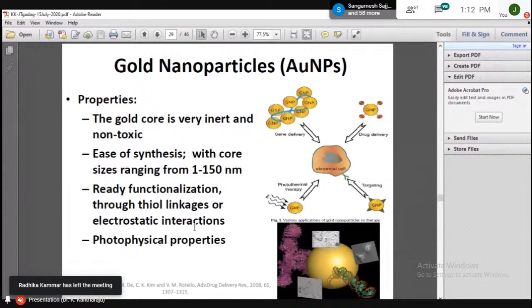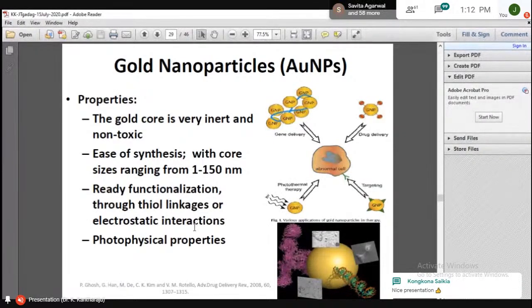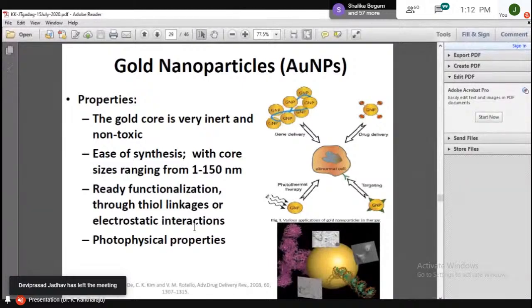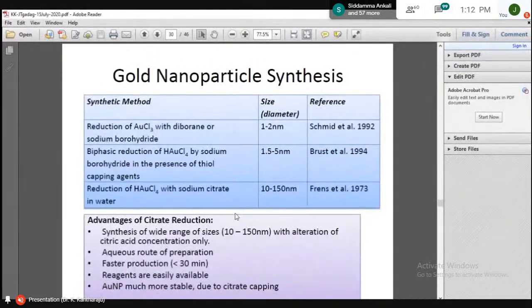Because our idea of putting that C-terminus cysteine is already planned, because in the literature we looked at, there is a very good chemistry developed for gold with sulfur. That is the reason, because obviously everyone loves gold. That is the gold salt we are used to. You already know about gold and all its properties. So, not much delay, because the ultimate point here is that the bond between sulfur and gold is very strong and well established and can be done.